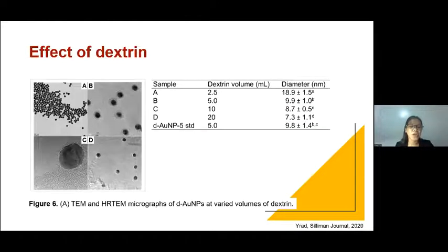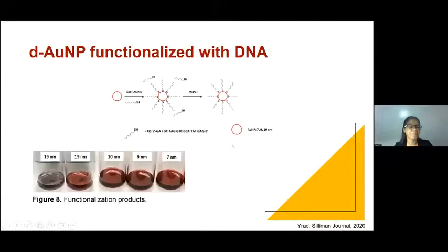Figure 6 shows HRTEM and TEM micrographs of D gold nanoparticles at varied volumes of dextrin. The micrograph reveals spherical shape without aggregation. From HRTEM analysis, it was observed that the diameter of the gold nanoparticle decreases as the volume of the dextrin increases.